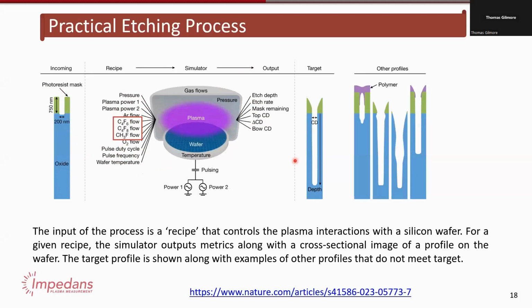And usually when you do this, you have some sort of target. So I mentioned earlier on, this is the CD, critical dimension, this is the depth. So this will have a certain aspect ratio. Here, this might be 20 to 1 or something like that. This is the target. But if the process is not quite finely tuned, you can get all sorts of different results here. So the top is closed, or it's bowing, and there's also other effects, like you get notches down below, or you don't get deep enough. So we really need to understand everything that's going on with regards to the ions and the neutrals in this case, in order to achieve these target profiles.